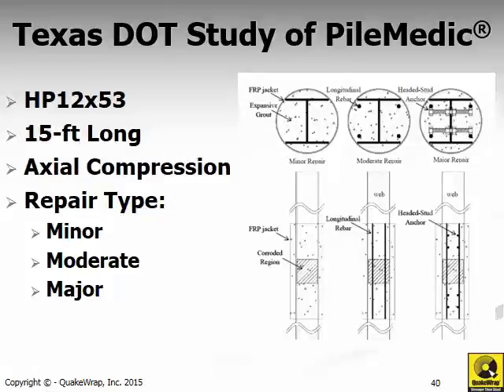There were 3 types of repairs that were performed depending on the degree of damage that these piles were initially subjected to. These included minor, moderate, or major repair. The minor repair only involved wrapping a shell around the column and filling it with grout. Moderate repairs included some longitudinal steel rebars in that annular space in addition to grout. And then major repairs included both the grout as well as the longitudinal rebar and some headed anchors.